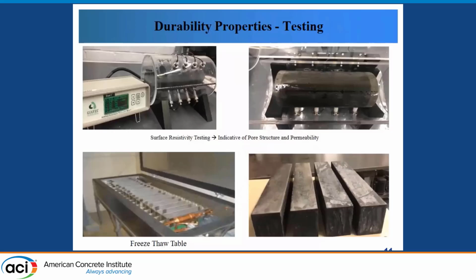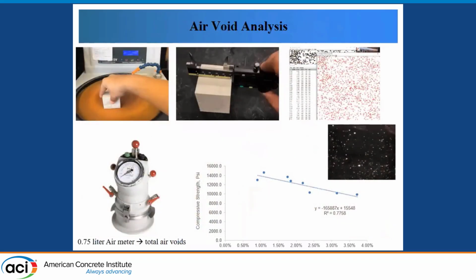In terms of durability properties, we have started to test UHPC surface resistivity, which is indicative of the pore structure and the permeability of the matrix. We also have started to test UHPC in the freeze thaw table. Another parameter to pay attention to is the amount of entrapped air. We have used two approaches. First, a mini air meter to measure the total air void contained in the fresh concrete, and second, filling the air voids of the ground UHPC surface with white powder, as we can see in the picture on the right hand side.